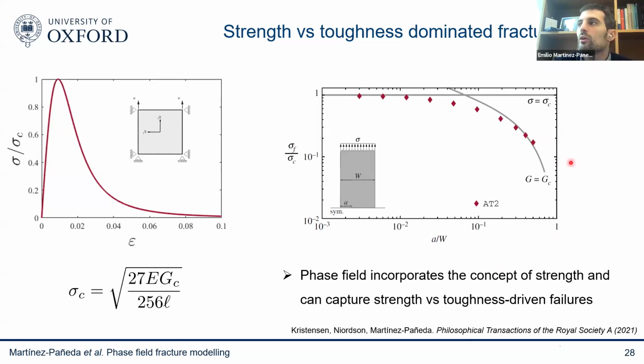The crack will grow based on this Griffith's energy balance, on the stress intensity factor. If your crack is very small, then you get yielding or you get strength-driven failures before fracture. So you have this transition from this type of failure to this fracture mechanics type of failure, and then industry uses one or the other depending on the size of the crack or their inspections.